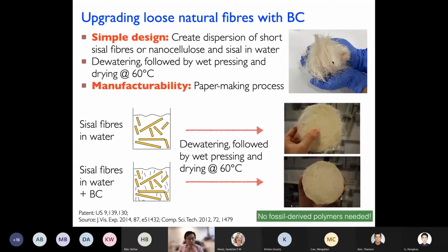So the process is rather simple. You disperse fibers in water, you add a small amount of these nanocellulose. In this case, we're using bacterial cellulose to start off with. You'll filter away the water, essentially dewatering, and then you press dry them at 60 degrees Celsius. So design is rather simple. Nanocellulose, in this context, bacterial cellulose, and some sort of loose fibers here, which in this case is sisal fibers, natural fibers. Put them together and it binds with each other.